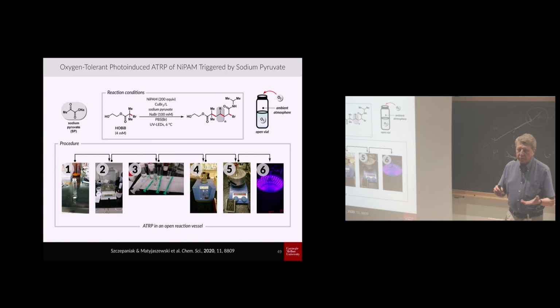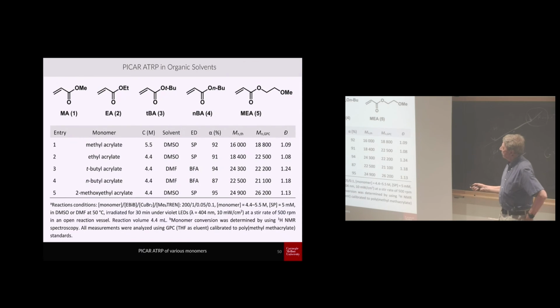But we sometimes would like to make it also very simple, so everything is done in completely open air. You can have syringes with your monomer and copper cocktail, if you wish, and then you plug it in, vortex it, and eventually put it in a reactor with a violet light, and polymerization starts this way. So this can be done for different monomers, not only water-soluble monomers, but you can do it also in organic solvents like DMSO or DMF, and this is a range of monomers, low dispersity, good control of molecular weights.